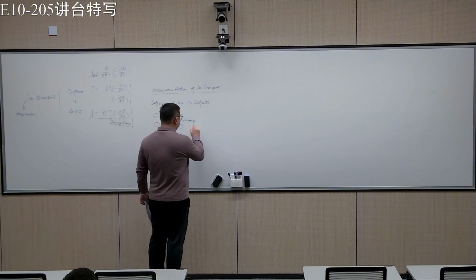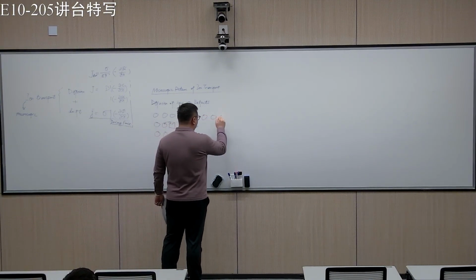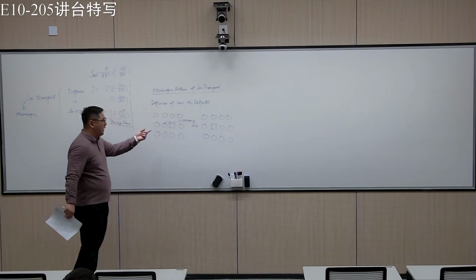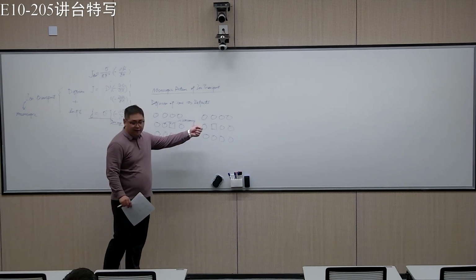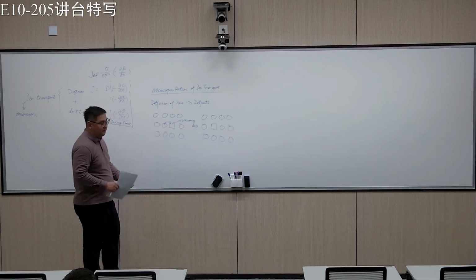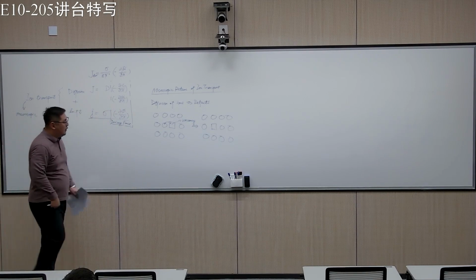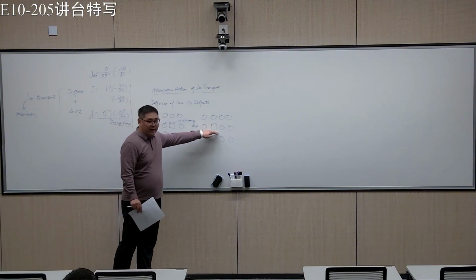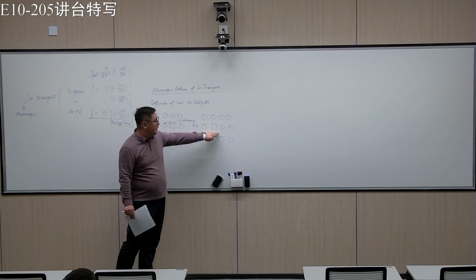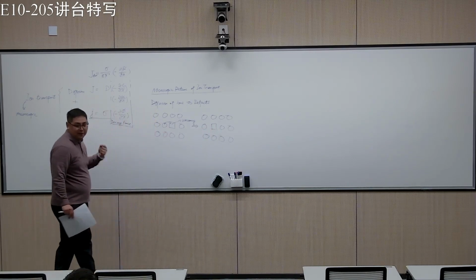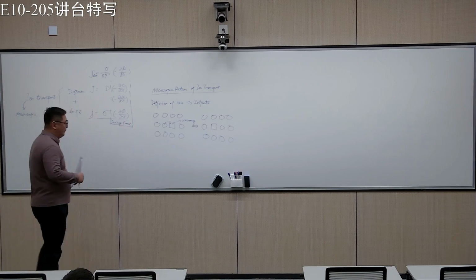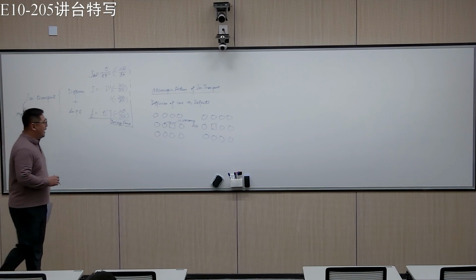Then the end result is that you have this kind of hopping mechanism. So something like this. Okay. So then you have a vacancy here, and then the jumping can just go up. Of course, the jump is kind of random, right? So the ions here can have the same probability of jumping back, right? Because here we assume that every ion here is the same. Okay. So it's basically a vacancy mechanism.